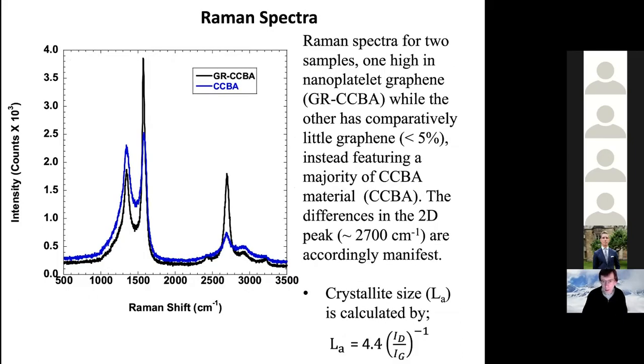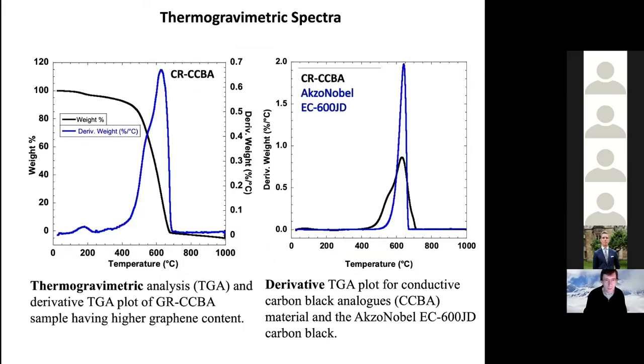We've also applied Raman spectra to the product as produced under the 2 nominal methane-argon ratio conditions. Again, the low ratio producing a mixture of the nanographene and graphitic carbon black analog, versus the other condition, producing exclusively the graphitic, or what you're seeing, CCBA, sometimes we have referred to it as conductive carbon black analog. I'll get to that as well. But there's a considerable difference, as you can see, in terms of the lamella length, referenced by the ratio of the D to G profiles, as well as the 2D signature peak presence or relative absence, although not totally disappeared, under the high methane-argon ratio. There's considerable distinction between the different products by XRD and Raman.